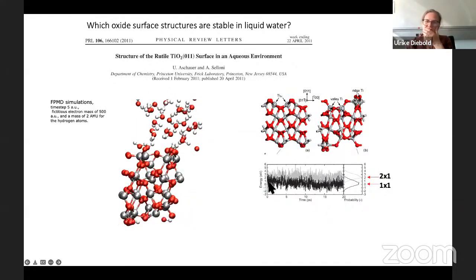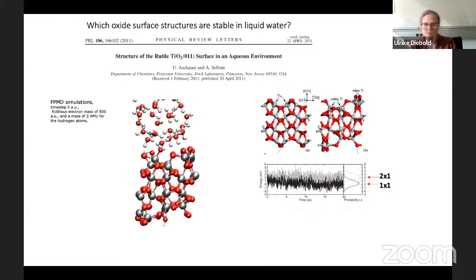This is the 2-by-1 surface reconstruction, the reconstructed one, and the 1-by-1, the unreconstructed bulk-terminated one. This is time step versus total energy in this first principles work. It seems like the 1-by-1 is more stable, even though in the beginning it is not, right? Which questions my own research area a little bit. Even if we know what the surface reconstruction is in ultra high vacuum, does it stay the same once you stick the single crystalline sample in liquid water? That's really a question that we have been asking ourselves.